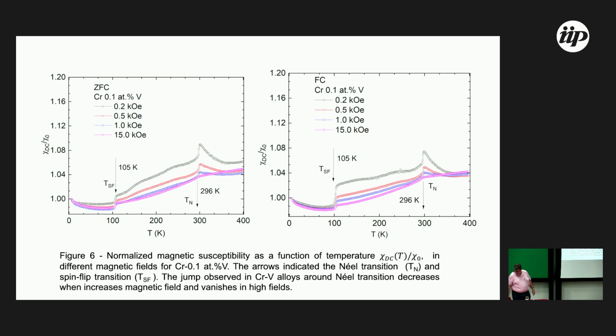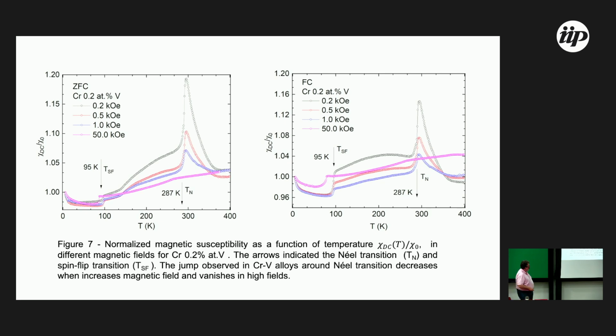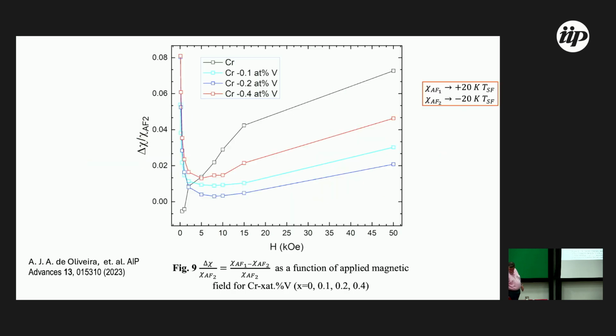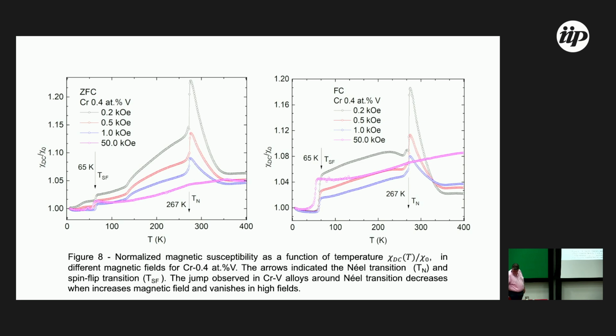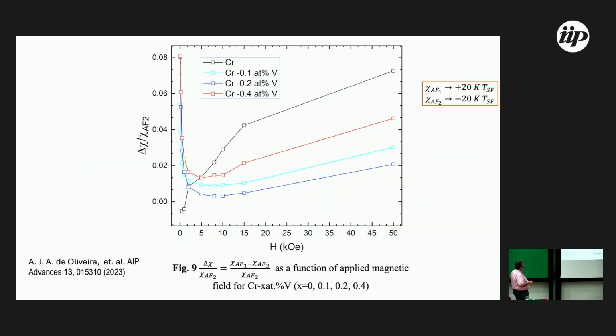When we observe 0.1%, observe the 0.2 kOe. The jump is bigger compared to 15, and compared with 0.4, for example, the jump at 0.2 kOe is more intense compared to the cooling down in the high magnetic field. And the proposal is to compare the size of the jump.